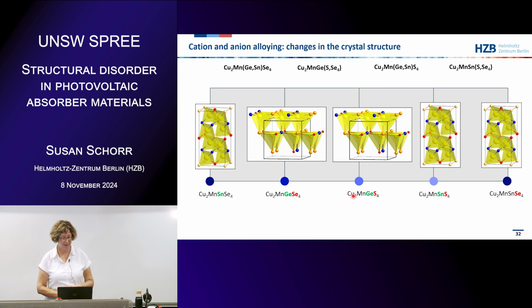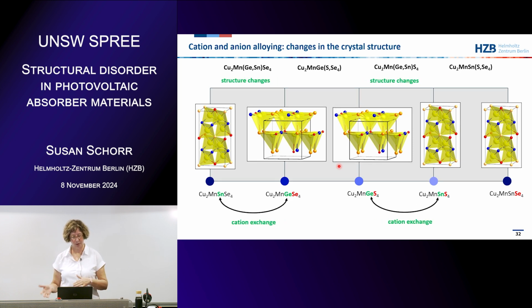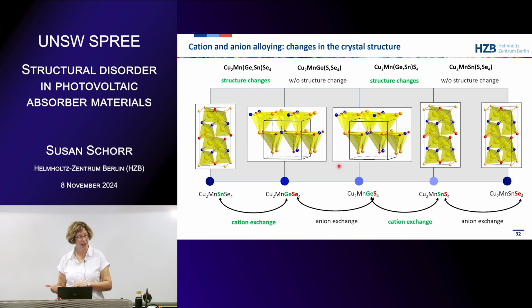We studied this series where we have manganese instead of zinc. Then we mixed the cations, so we exchanged germanium and tin. And we also did an anion alloying, sulfur and selenium. The copper manganese tin selenide and the copper manganese tin sulfide crystallize in the stannite structure, and the other two with germanium crystallize in the Wurtz-stannite type structure. So that means we will have a structural change when we exchange the cations, and we will have no structural change when we exchange the anions.